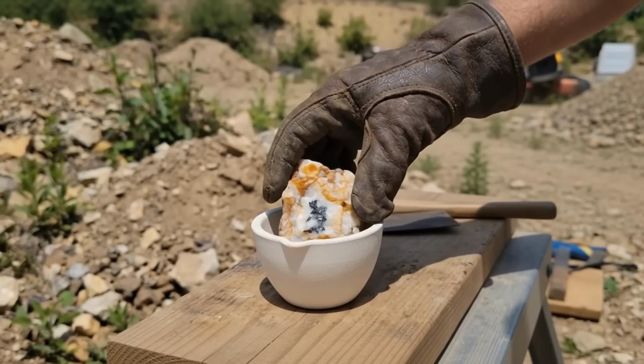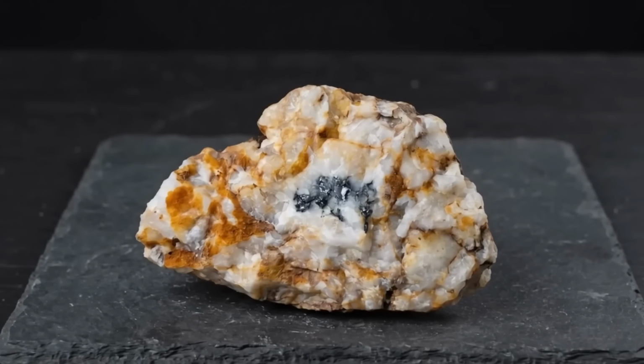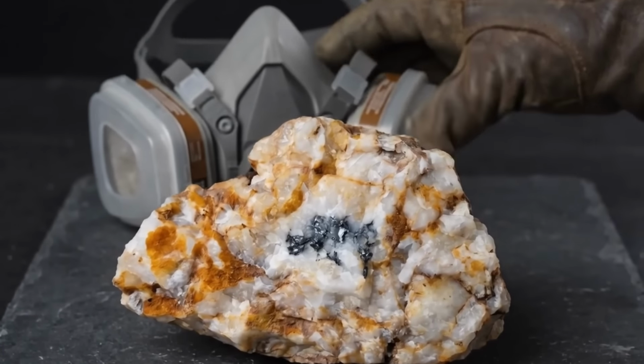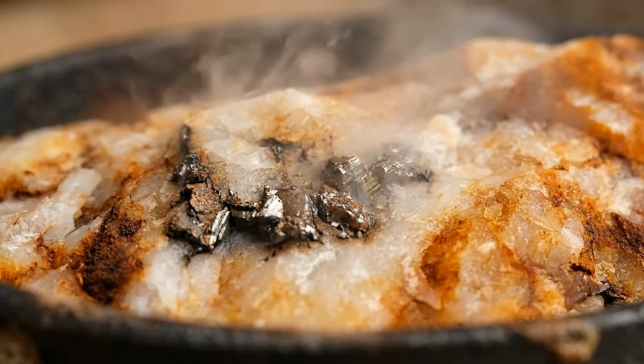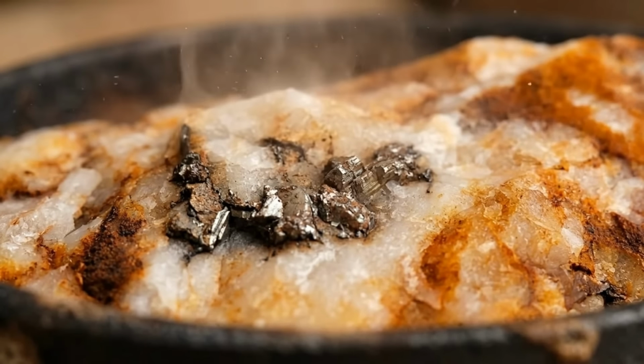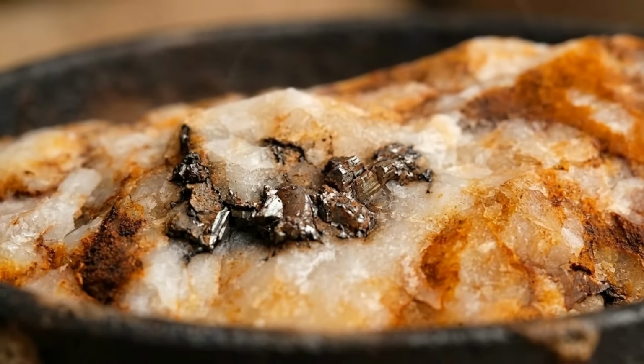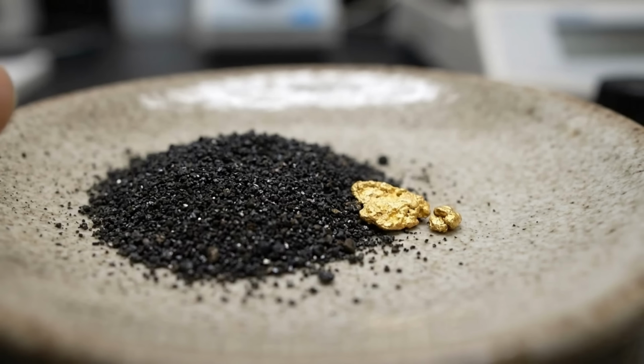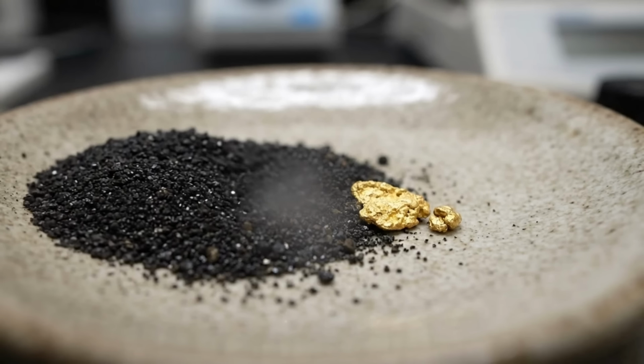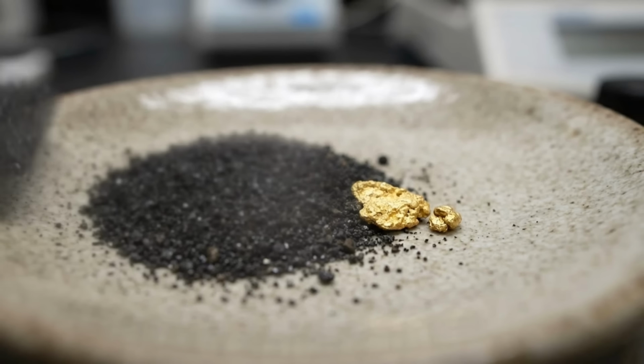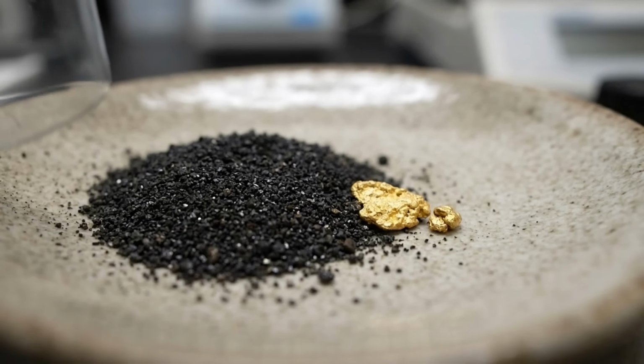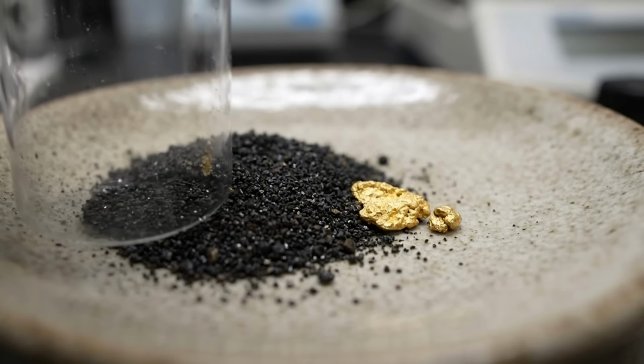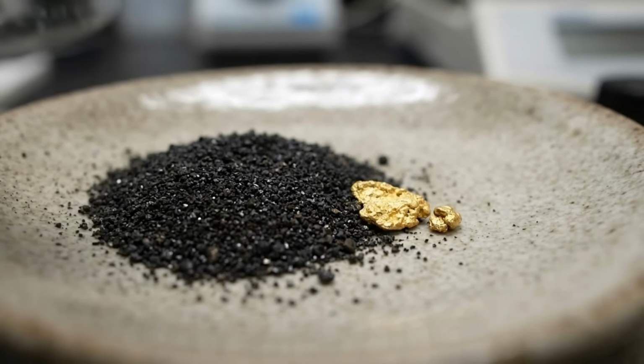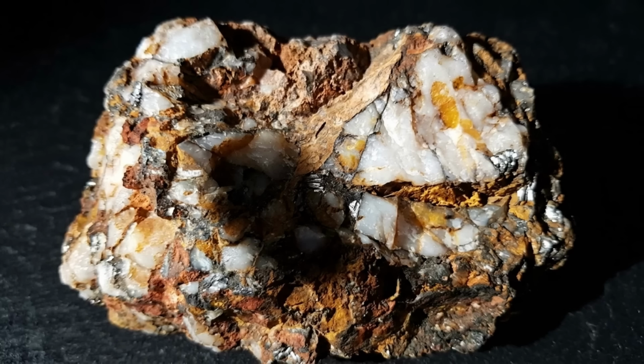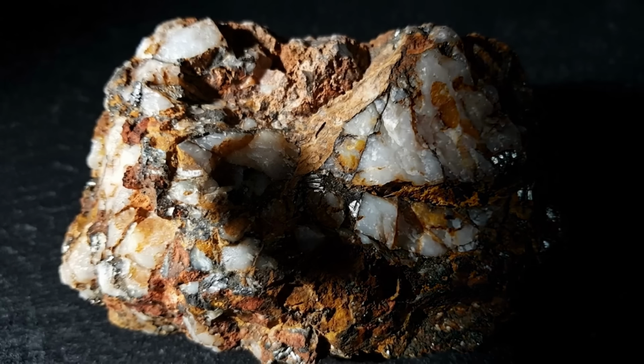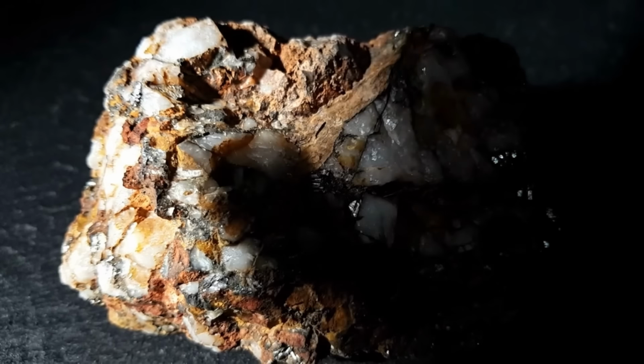Galena has a distinctive metallic gray color and breaks into perfect cubic shapes, making it easy to identify in the field. To extract gold from Galena, you first roast it to convert the lead sulfide into lead oxide and drive off the sulfur. Then, you smelt the roasted material, and the lead melts at a relatively low temperature of just 621 degrees Fahrenheit. As the lead melts, any gold or silver present will dissolve into the molten lead, and you can then use a process called cupellation to separate the precious metals.